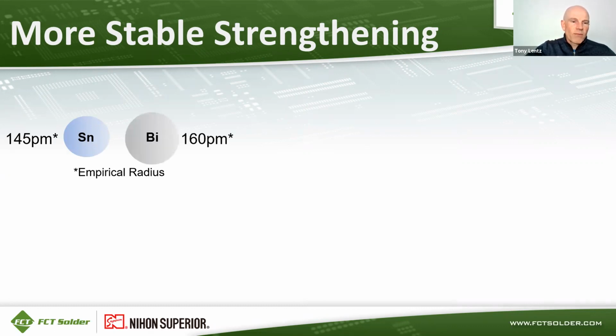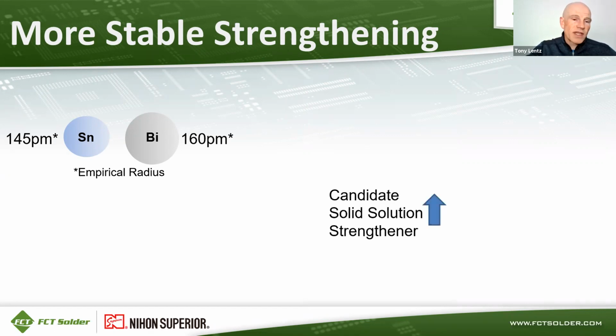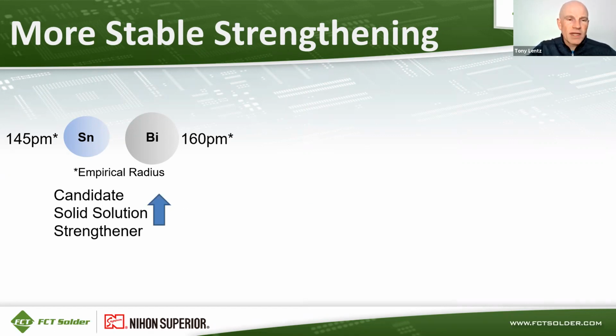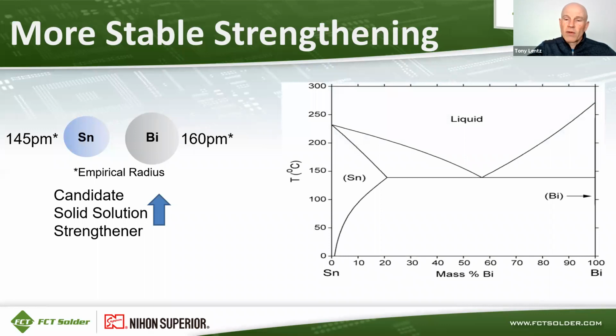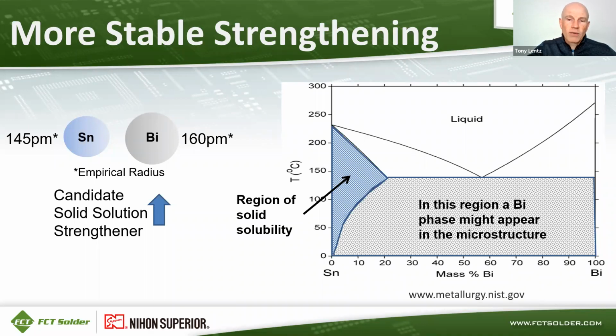So tin and bismuth have pretty similar empirical radii. They are 145 picometers versus 160 picometers, which means that bismuth could potentially dissolve into tin and integrate into the tin matrix pretty readily. Here's a phase diagram for tin and bismuth. In the blue highlighted region, bismuth is fully dissolved into the tin and evenly distributed throughout it. That's the region of solid solubility. And in the gray shaded region, bismuth might precipitate out and could appear as pure bismuth islands in the microstructure.